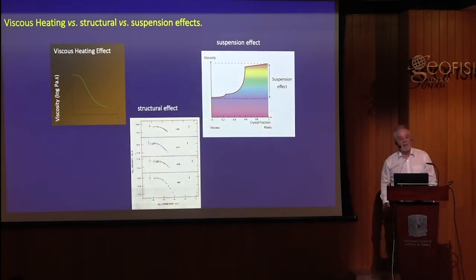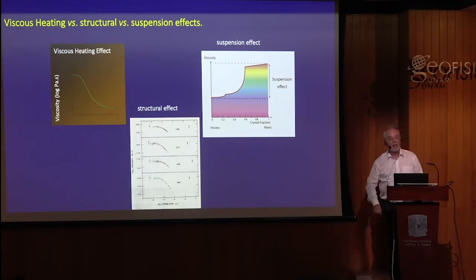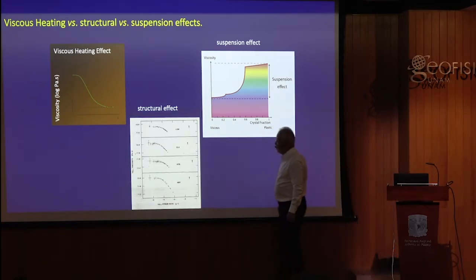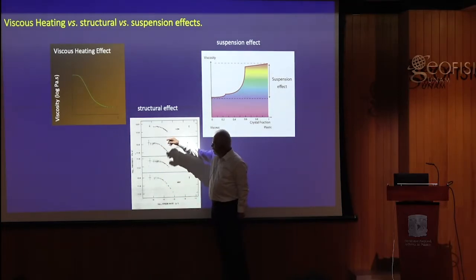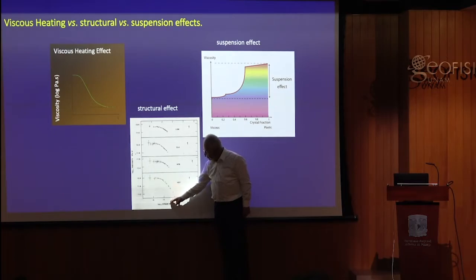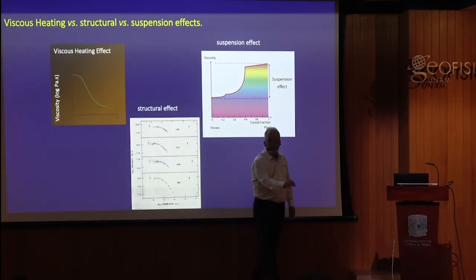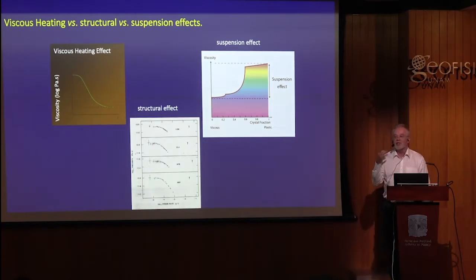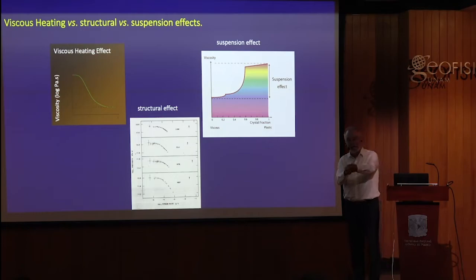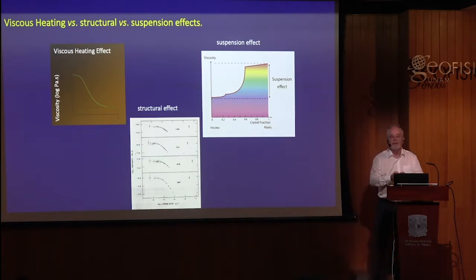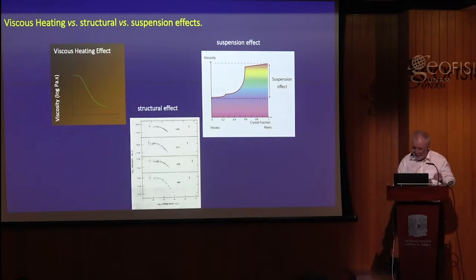Three things are actually happening at the same time when we blow these rocks up. We have a viscous heating effect, which is potential, because these are high stresses. It can actually start contributing to the thermodynamic energy, the enthalpy of the system, by pumping energy into the system through shearing. We have a structural effect, which is that the structure of the liquids, these are volcanic liquids, and they all start to collapse in viscosity as a function of a certain strain rate. This onset of non-Newtonian viscosity, viscosity which depends on strain rate, is the structural destruction of the liquid. You literally, it's something which always fascinates me, you mechanically tear the thermodynamic state of the liquid apart. Talk about putting mechanics and thermodynamics together, okay? And the diffusion is not enough to put it back together again. So it's going to be complex.